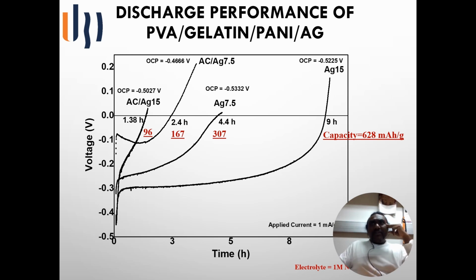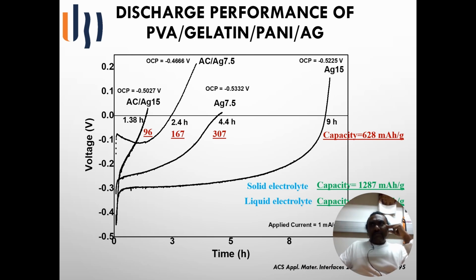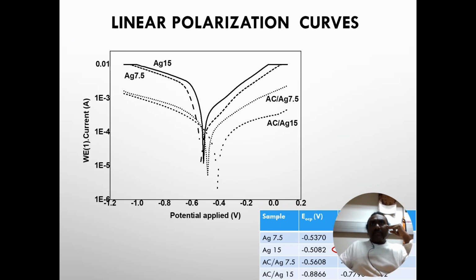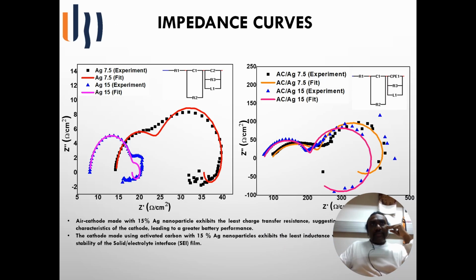We have obtained a maximum of 628, which is around 50% below the reported values. And here are the linear polarization curves. These polarization curves also clearly say the silver 15 weight% nanoparticles showed very high corrosion behavior. These impedance curves also support the electrical discharge performance, as 15 weight% silver nanoparticles exhibit the least charge transfer resistance.